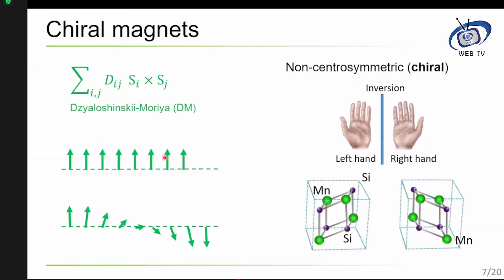Normally, in magnets, each atom carries a spin, and if you apply a magnetic field, they all align. They are nicely aligned. These are normal magnetic materials. A famous example is yttrium iron garnet. However, there is an exchange interaction, the Dzyaloshinskii-Moriya interaction. It is mostly zero for normal magnetic systems, but in the system I am talking about, it's non-zero. It tries to align spins perpendicular to each other. Obviously, it cannot align them perpendicular. It's a very small contribution, but it will tilt your magnetic structure away. And this is what we are interested in. We are interested in twisted magnetic structures.